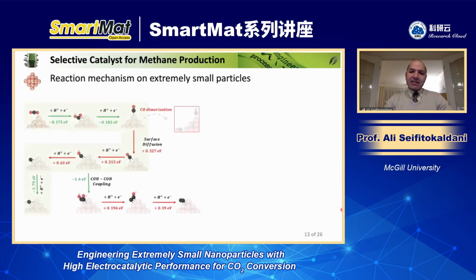So coming back to the mechanism, as I was saying, we always were using the slab model, which means you are using a periodic model in DFT computation. So it represents a large surface area. It doesn't really represent an isolated small particle. So this time we said, let's look into the reaction mechanism following the same path based on the literature and our prior work, but on these pyramid-shaped particles to see what happened.